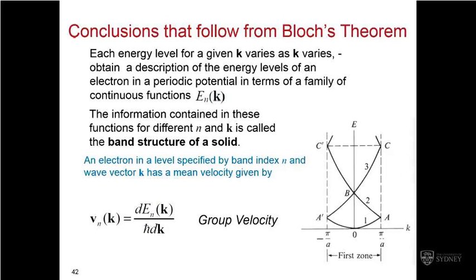And when we introduce a potential in there, what we find later on is we'll get little band gaps opening up. But basically, what we've got here, these dispersion curves are called the band structure of the solid. We could have called our free electron curves the band structure of the solid, but in that case, our solid had no potential. It was just like a repeating box.